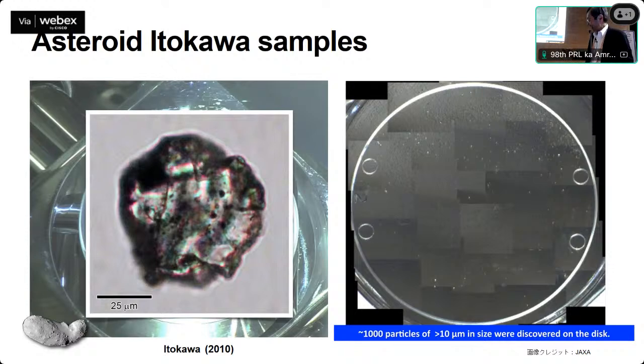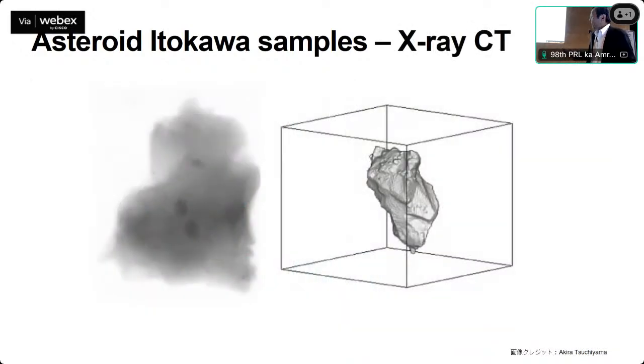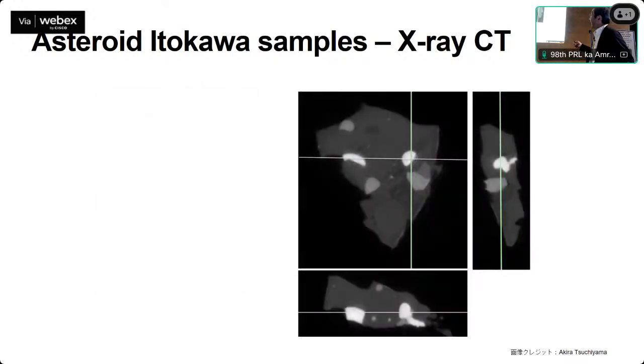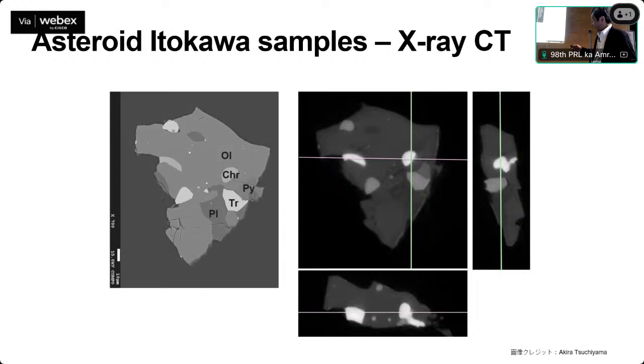And in order to characterize and identify these minerals, we take X-ray CT. So this is a density map of one particle, an Itokawa particle. Then, in order to analyze these particles, we consider how to cut them. Then this plane is most favorable. So we grind and polish this surface. Then a similar contrast we can obtain.